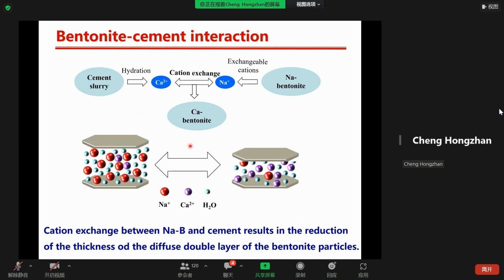Okay, here is about the bentonite cement interaction. Previous studies have demonstrated that cement can chemically affect the hydromechanical behavior of the bentonite. The original sodium ions in the bentonite interlayers were exchanged with the released calcium ions from the cement slurries, resulting in calcium bentonite, and the diffuse double layer of bentonite particles was reduced.